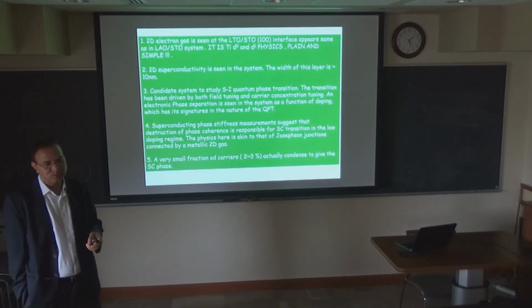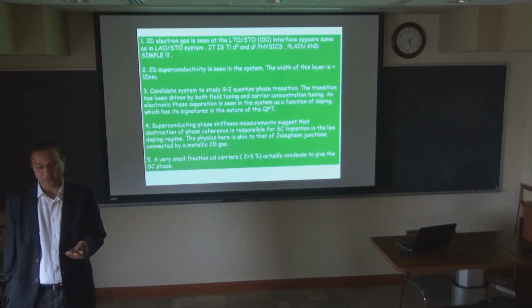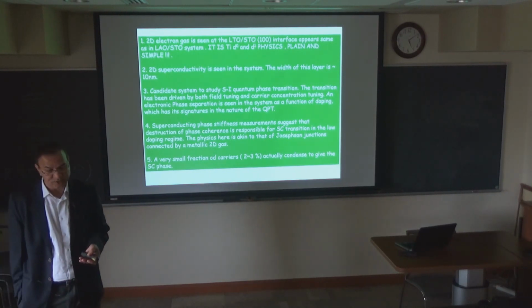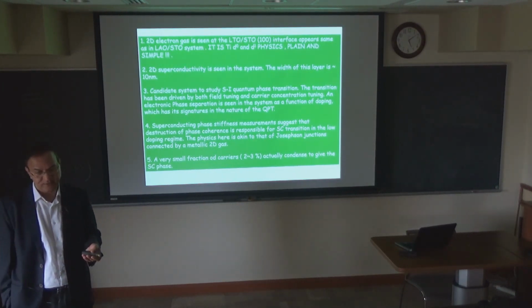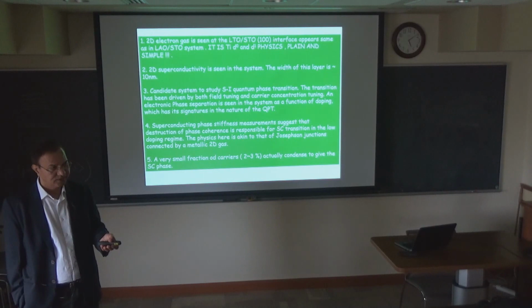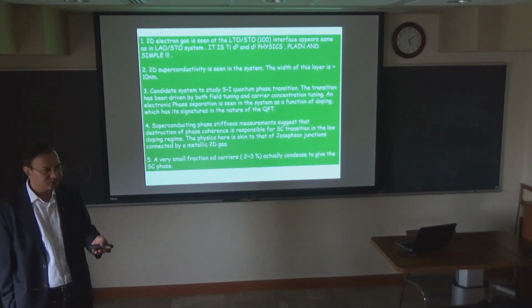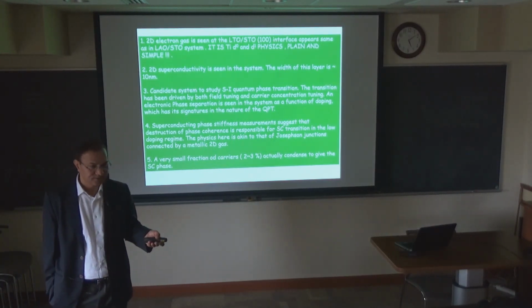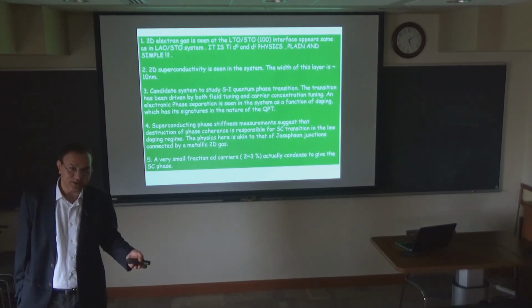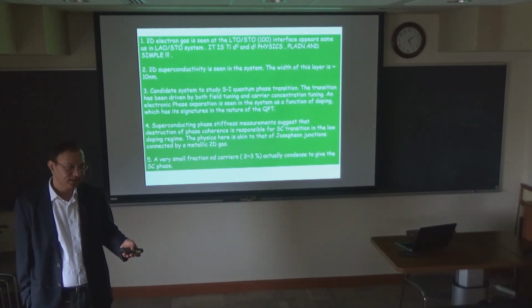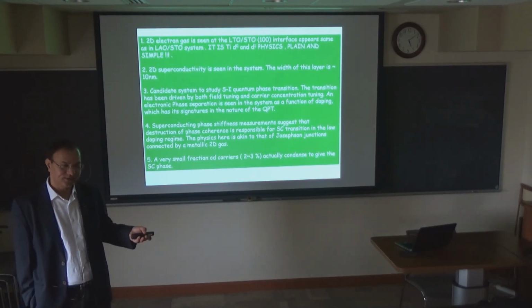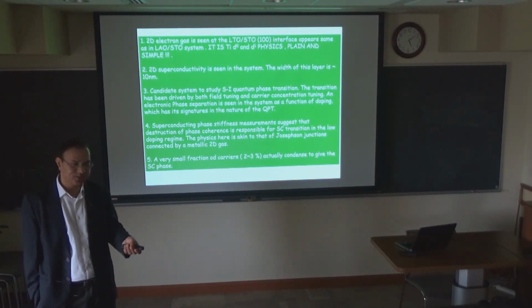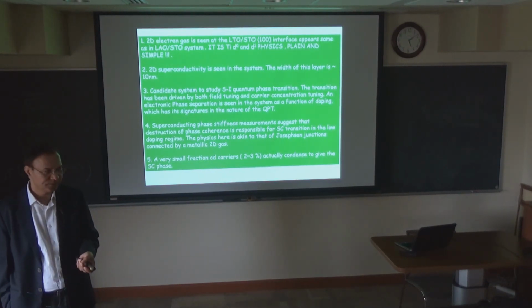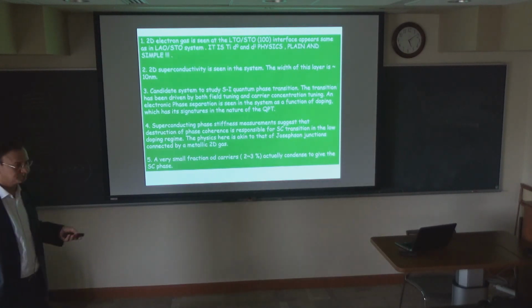These are very good systems to study quantum phase transition in 2D, because earlier people used to make thin films and vary the disorder by changing the film thickness. So every sample is different. Here you have one sample, and you are changing the carrier concentration by simply applying the gate. So it's a much better system that way.